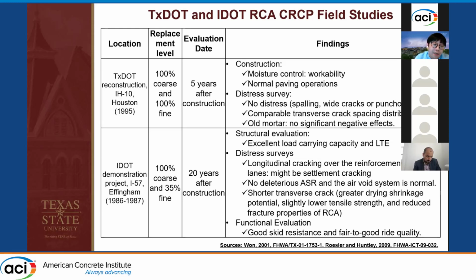and they did not find the old mortar had significant negative effects. And also Dr. Rossler from University of Illinois, they also did a field study on existing CRCP concrete on I-57. And 20 years after construction, they did some field studies. They also did an FWD test. They found those CRCP RCA sections had excellent load carrying capacity and load transfer efficiency.